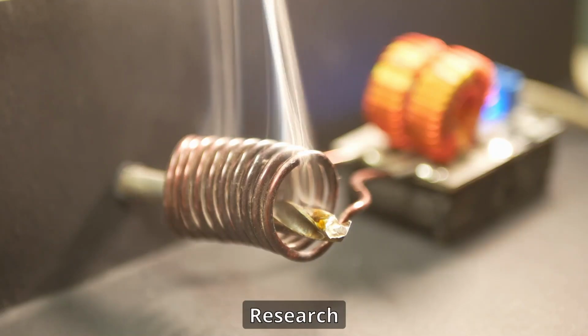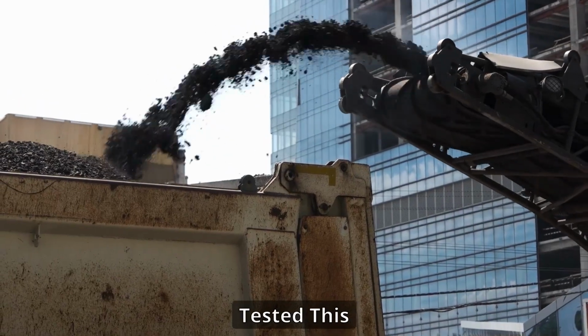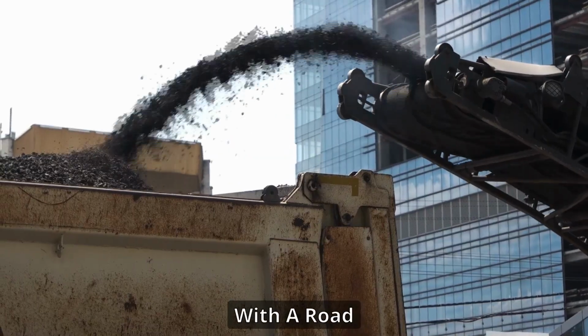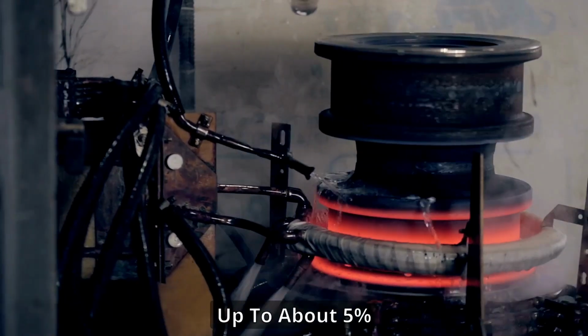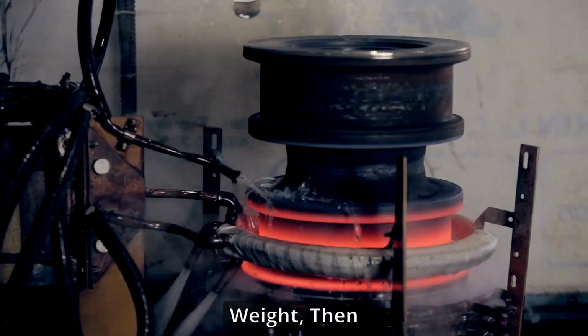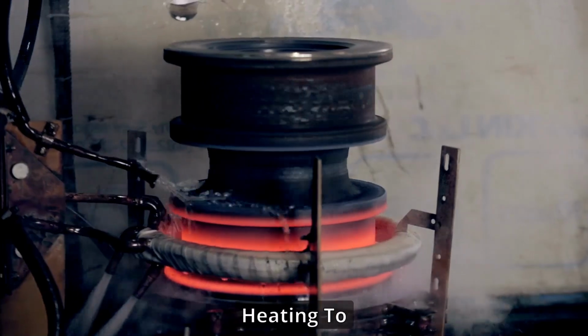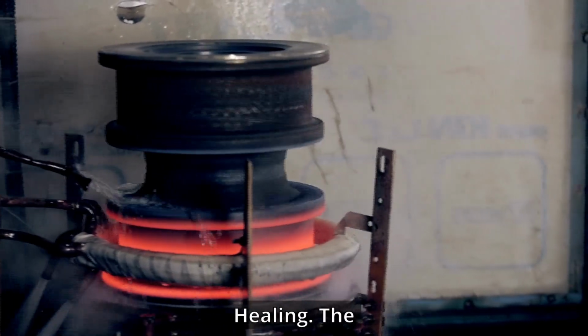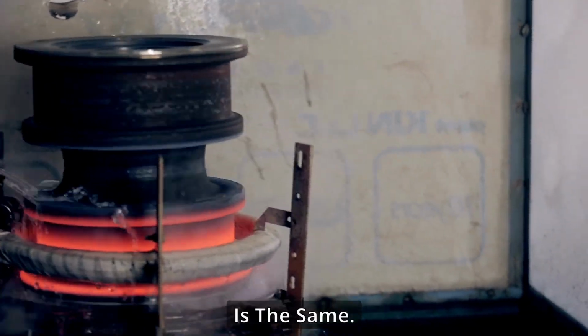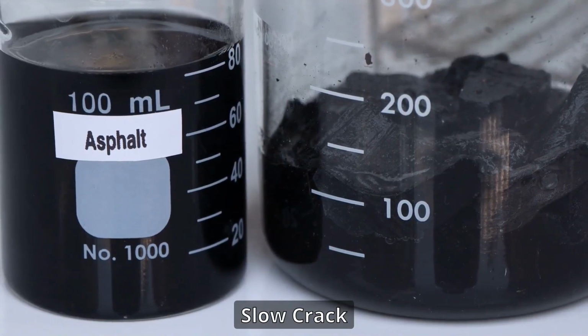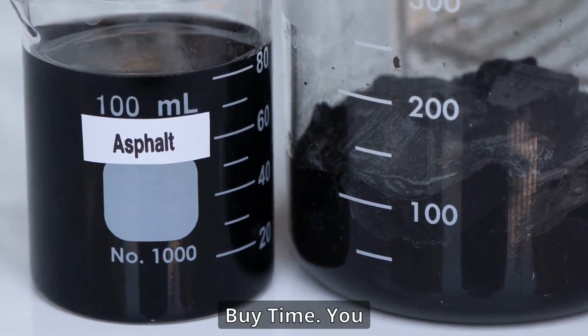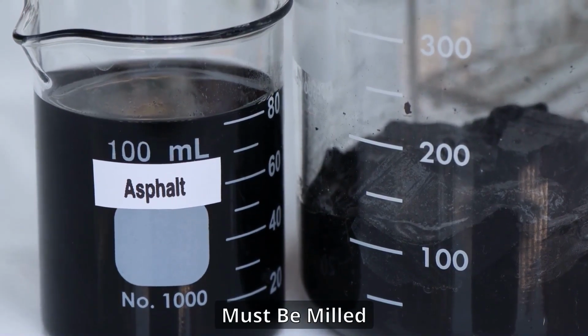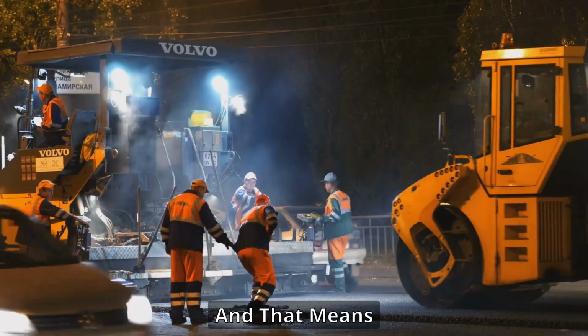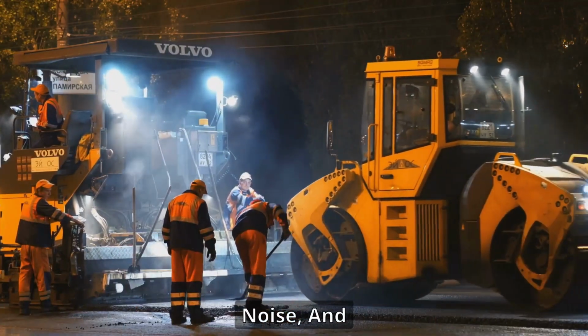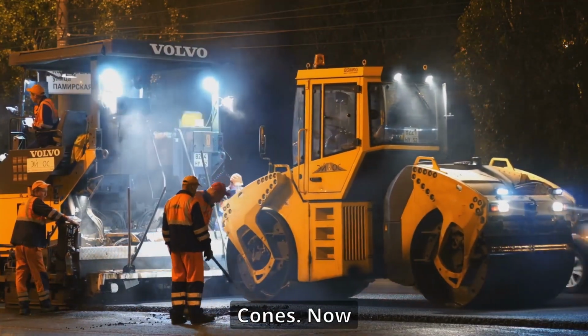A transportation research report in Louisiana tested this idea in the lab with a road surface mix that included up to about 5% metallic fibers by weight, then applied induction heating to damaged specimens to stimulate healing. The bigger message is the same. If you can slow crack growth, you buy time. You delay the day when a road must be milled and replaced, and that means fewer closures, less noise, and fewer nights of orange cones.